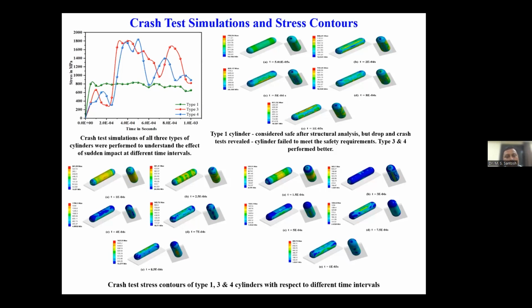And in all these studies, it was quite evident that type 1, although it was not much deviated from the actual structure, could easily undergo deformation and rupture the cylinder and cause a lot of damage compared to type 3 and type 4. Overall, type 4 came to be a better performer, despite the crash test being subjected on all three. Type 4 evolved to be a better material compared to the type 1 and type 3 materials.